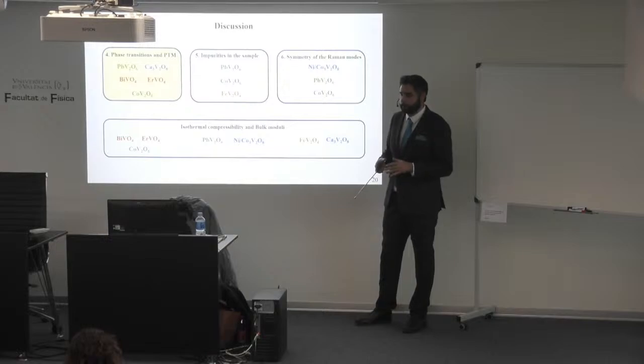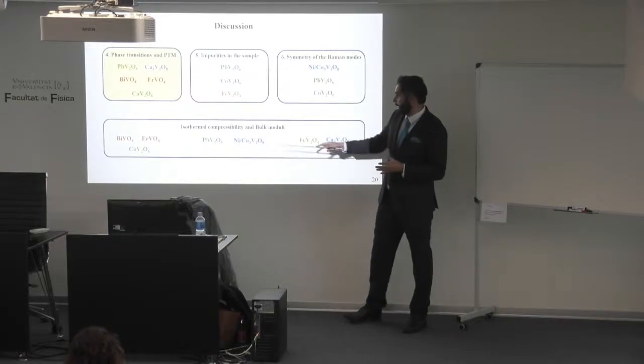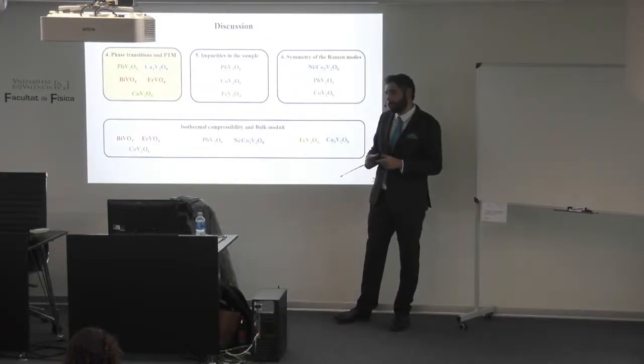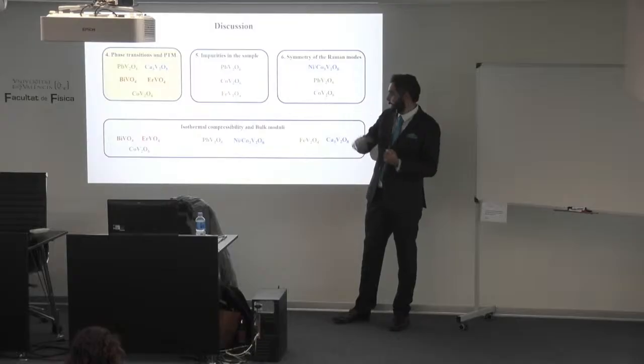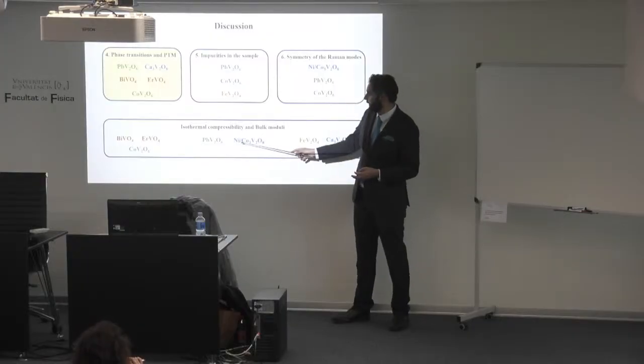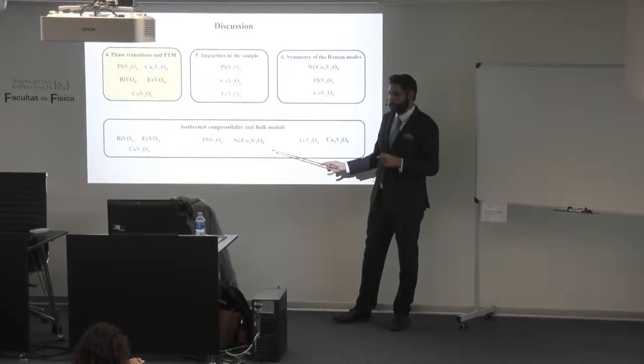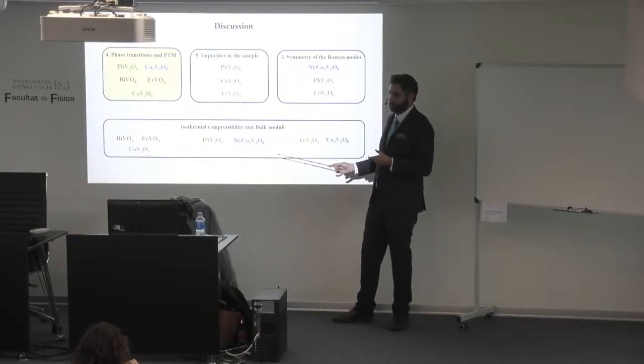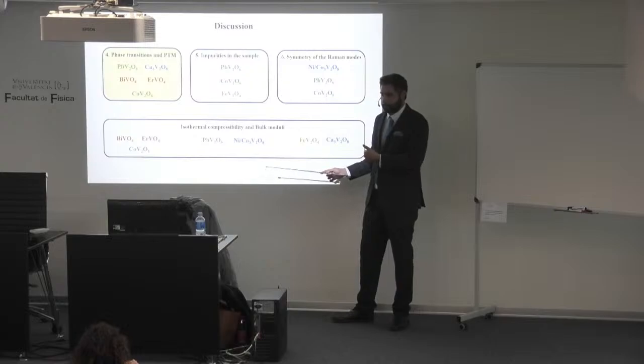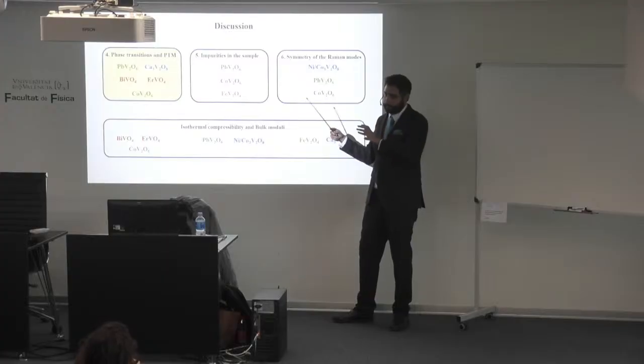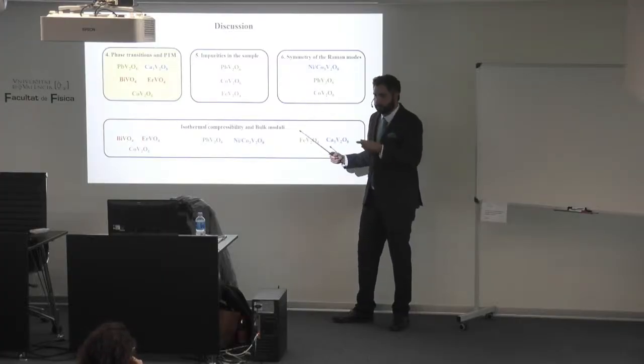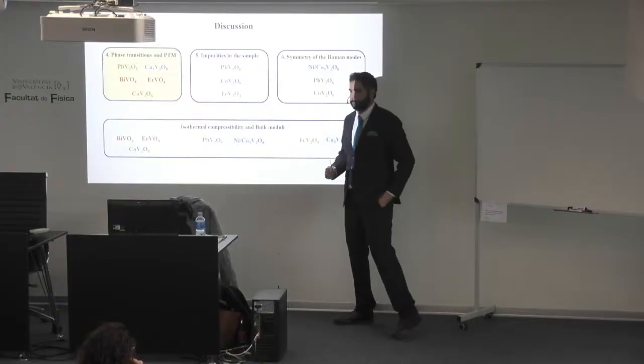orthovanadates, we saw that they have the same isothermal compressibility for all axes except the b-axis. And in the b-axis, they mainly have the nickel or the cobalt metal located. So in the axis where we have this metal, if we change it, we see that the nickel orthovanadate acts like a compressed version of the cobalt one. And this is afterward reflected in the pressure evolution of the modes. We see that they evolve the same, or they cross similarly, but later in pressure because of this relation.